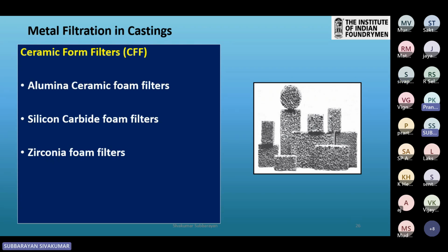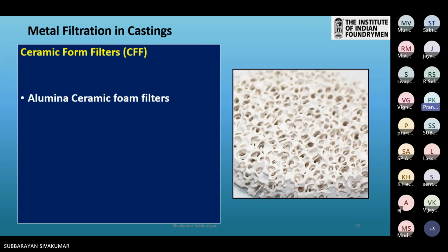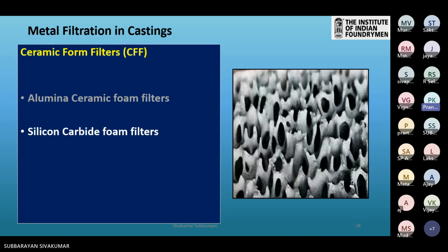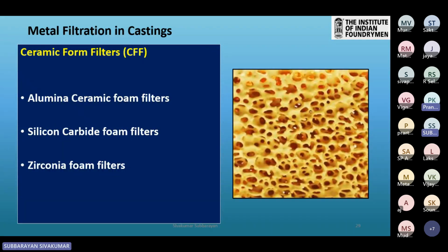Alumina ceramic foam filters, silicon carbide foam filter, which is predominantly used in many foundries, and zirconia foam filter. Alumina is almost white in color. Silicon carbide filter is light gray and dark gray in color. Zirconia foam filter is pale yellow. So out of these three, silicon carbide is being predominantly used because of its versatile advantages like effectiveness of the filtration and easy to use, and it is cost effective compared to the other two.